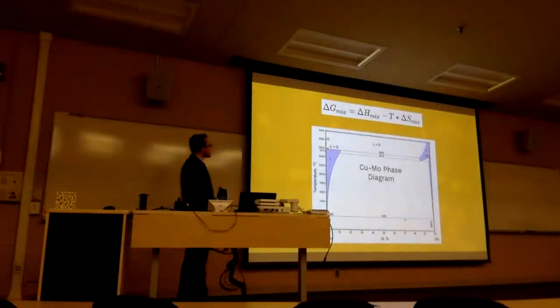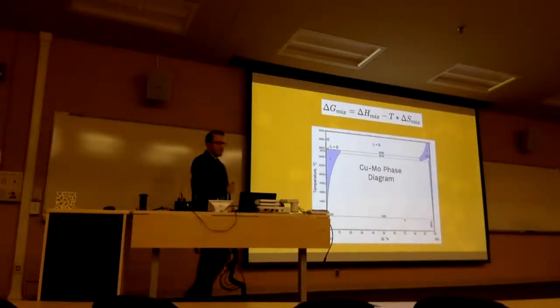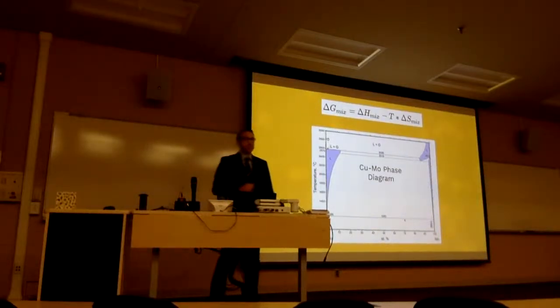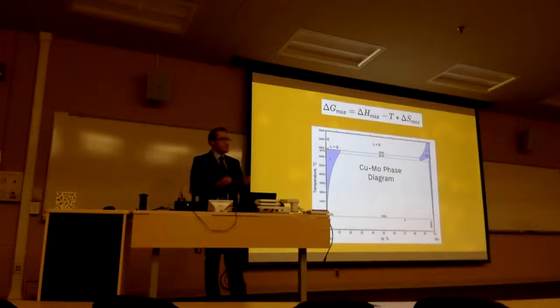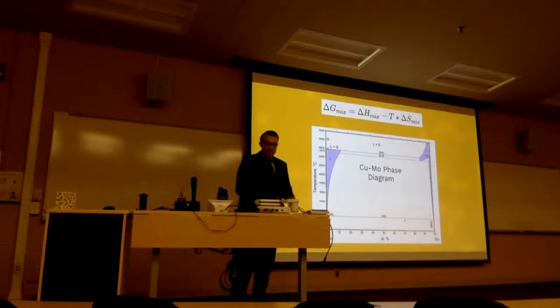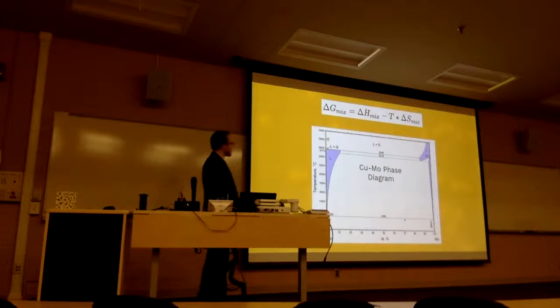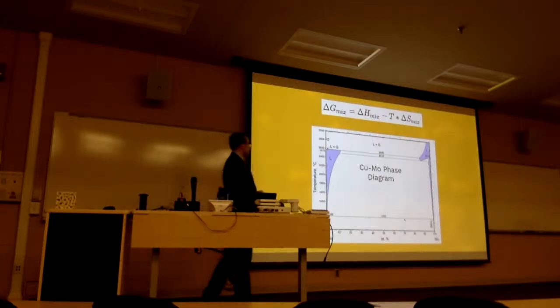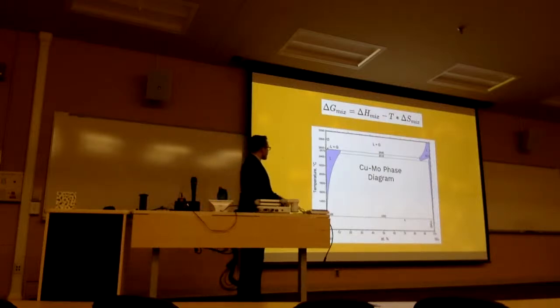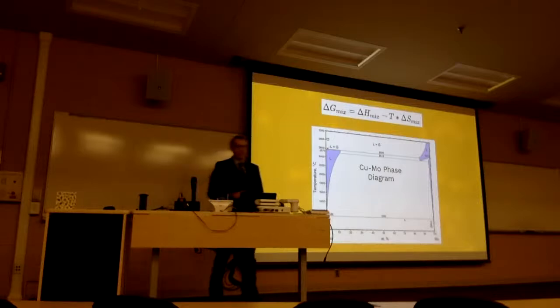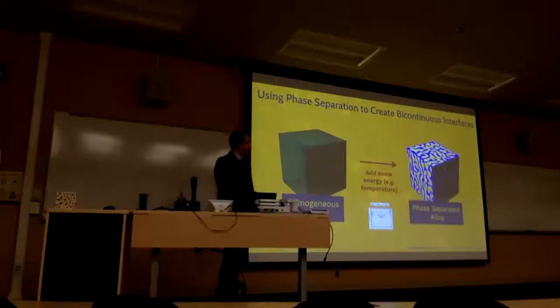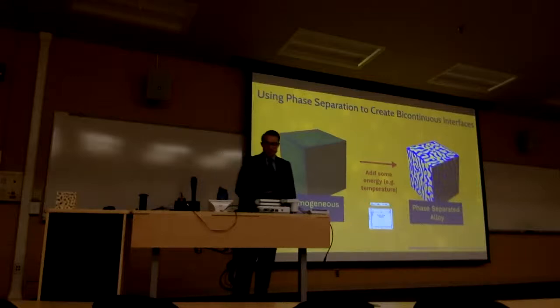What are those combinations? Well, if we look in our thermodynamics textbook, those are materials with high heats of mixing. These are materials that do not like to mix. For example, the copper-moly system. This is a copper-moly phase diagram where you can see it maps out temperature and composition, and you can see that this system is very insoluble. An alloy or thin film that looks exactly like this on the right.